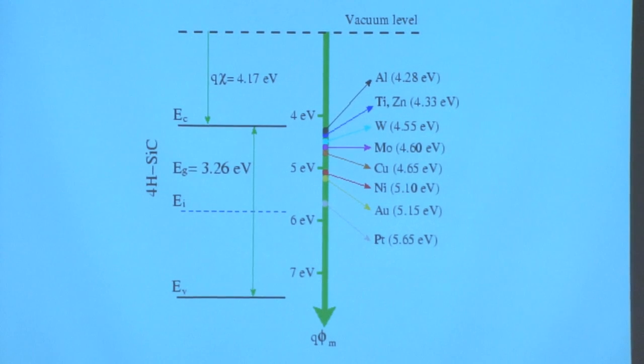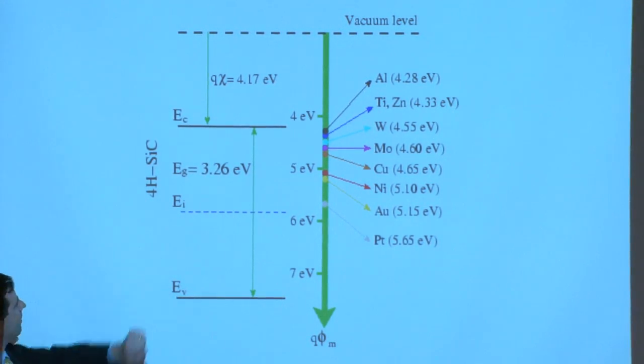So on the left is an intrinsic semiconductor? Yeah, it's pretty close to intrinsic. It's a little N-type, it looks like, but it's pretty close to intrinsic. In this case, just a variant of silicon carbide. There are many polymorphs of silicon carbide, meaning same composition, same silicon-carbon ratio, but different crystal structures depending on how it was grown.